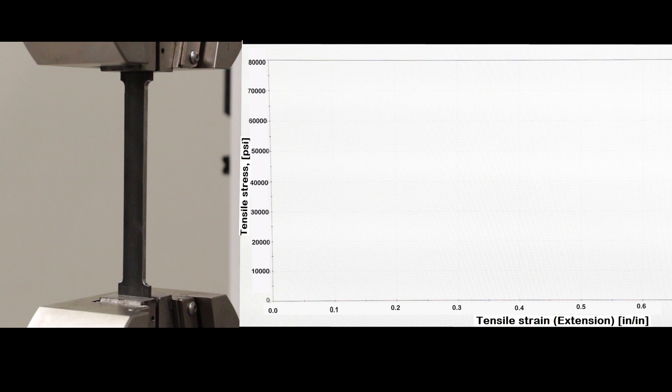One of the interesting things you'll observe as the test goes on is that as the tensile specimen is stretched out and elongated, the brittle material on the surface will fracture. You'll see those cracks developing as the specimen gets longer, while the inside material deforms plastically.